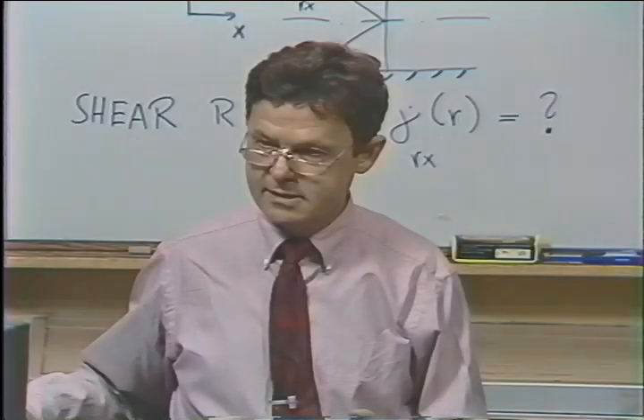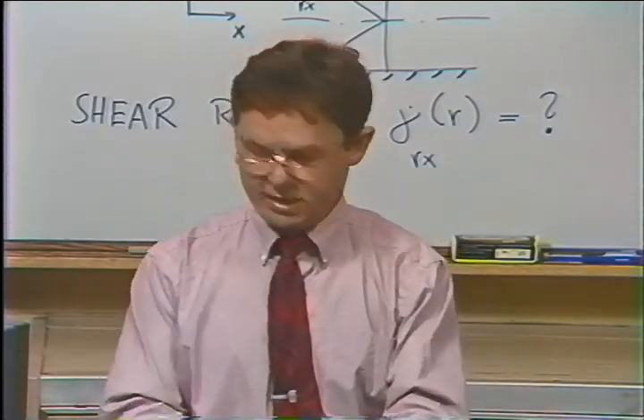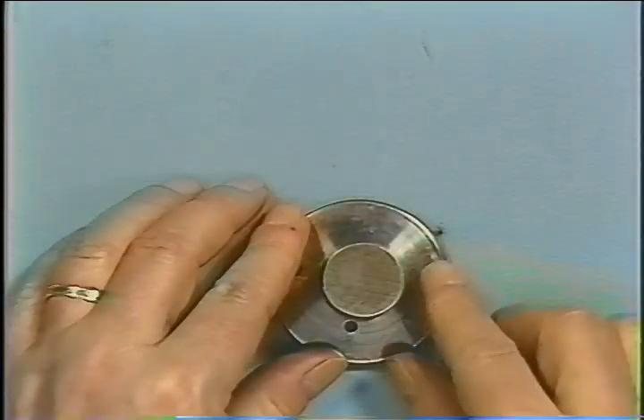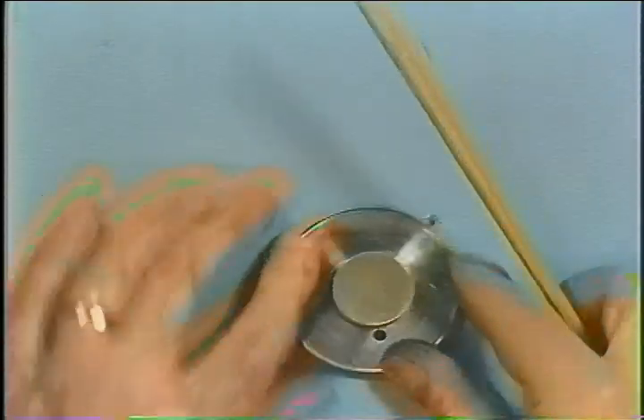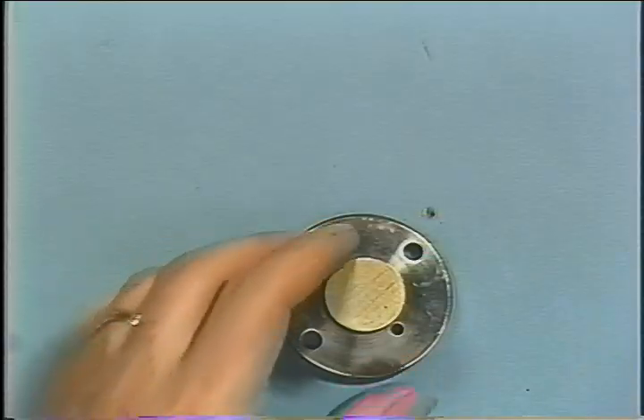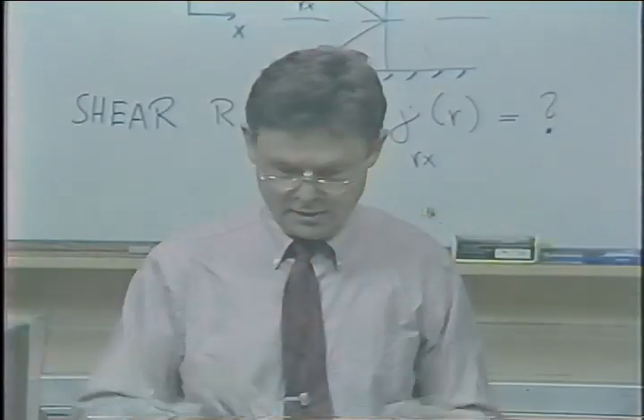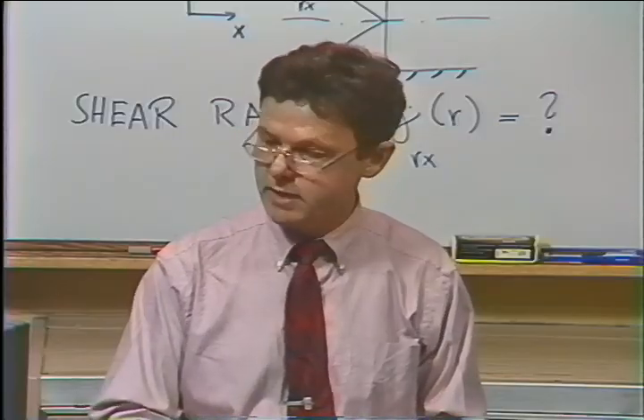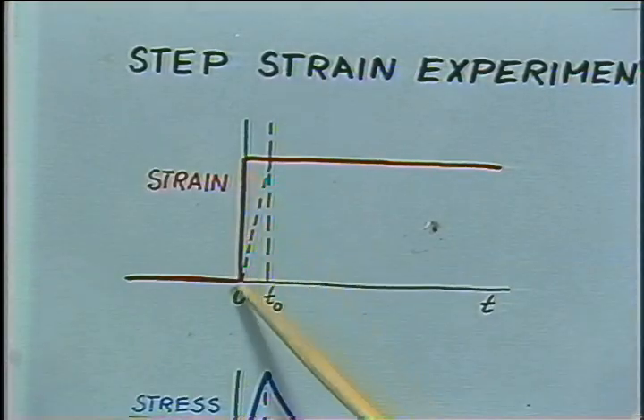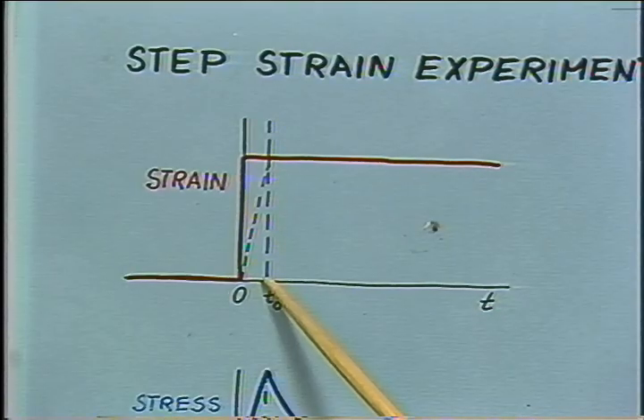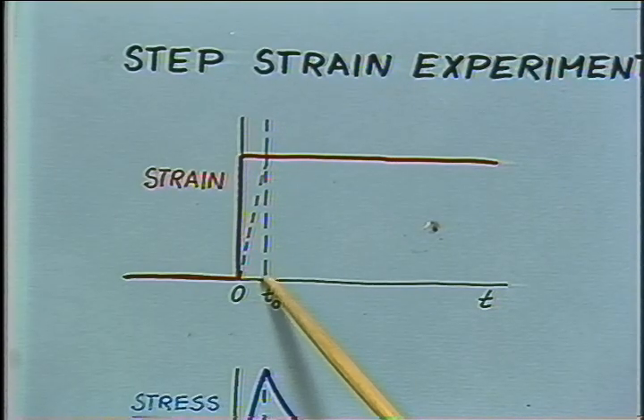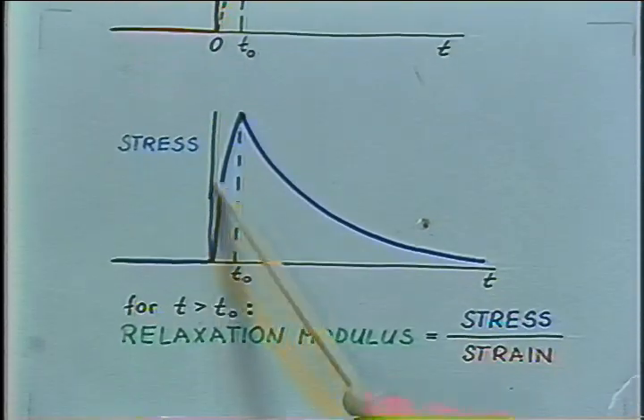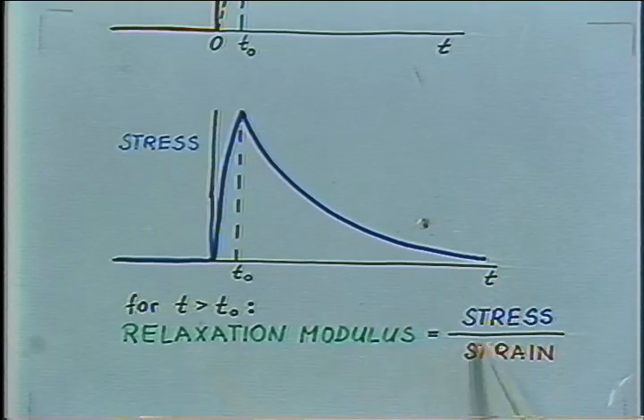We would like to use the cone and plate rheometer to determine this modulus by imposing a deformation on the sample. We would put the sample here in between, and then we put a sudden rotation into the sample. We would deform the sample. We would input a strain into the material. It would still need a finite rise time, but this is on the order of a few milliseconds, maybe 100 milliseconds or so. So the sample would be deformed, and a stress would be introduced into the sample, and then the stress is relaxing as a function of time.